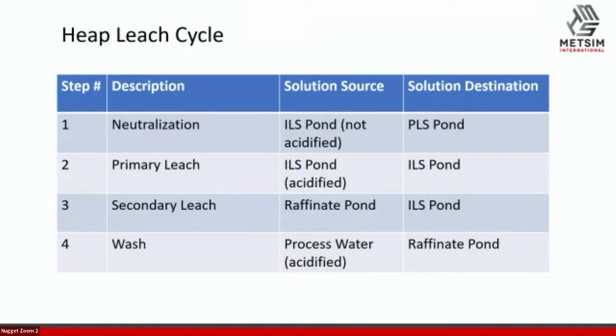If you're familiar with nickel laterites, a lot of people think they shouldn't be heap leached. I remember when our colleague Ann Oxley said they were going to heap leach a nickel cobalt laterite, I said, you're going to build a giant swimming pool. But what that means, there's a lot of residual moisture, 22, 25, 26%. I think we even saw at some points dynamic moisture during the leach cycle. What that means, we've got a lot of dissolved metal in inventory. So process water wash, 5 gram per liter acid, just to keep that pH down. And that would then go into our raffinate pond. So we ran that leach cycle, mostly adhered to that leach cycle for heap 0, heap 1, and heap 2. Heap 0 was a bit of a trial to get us started there.